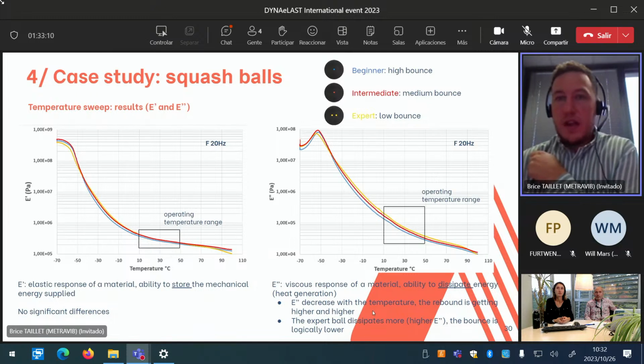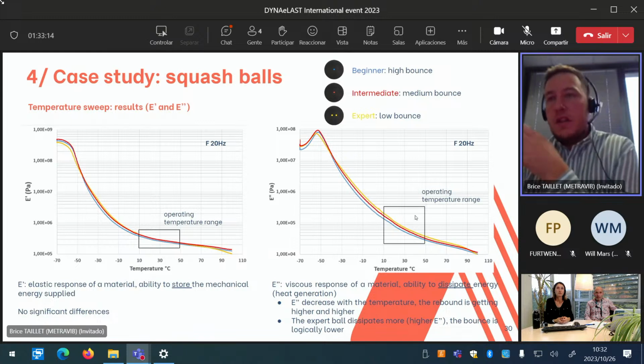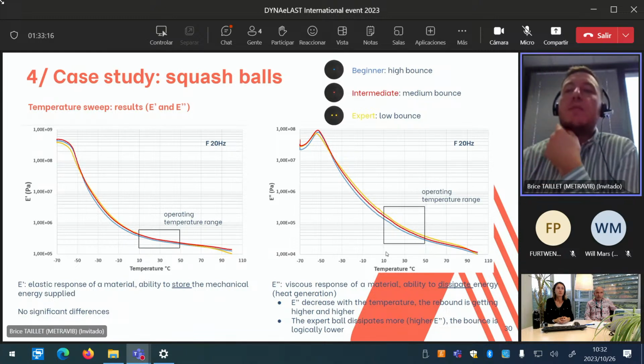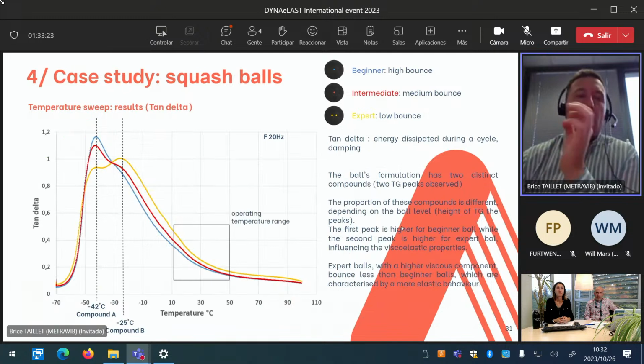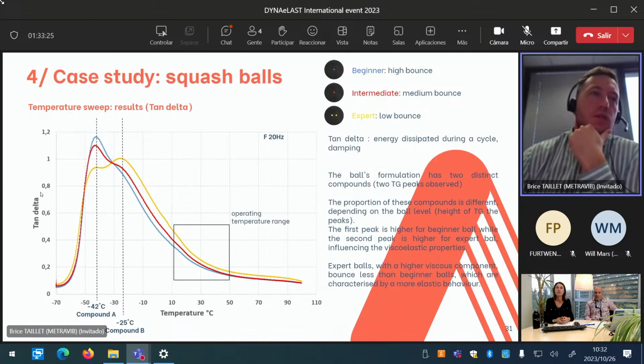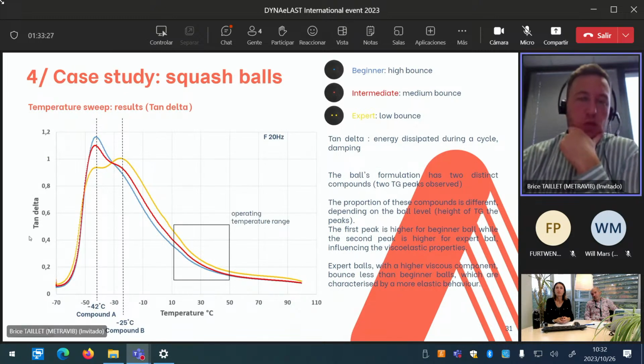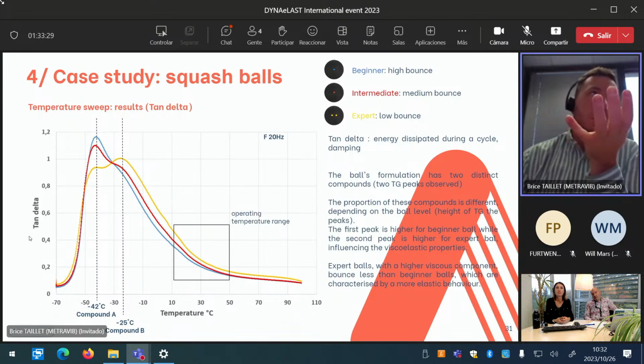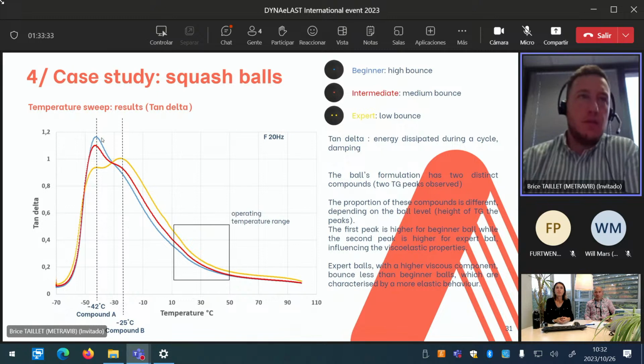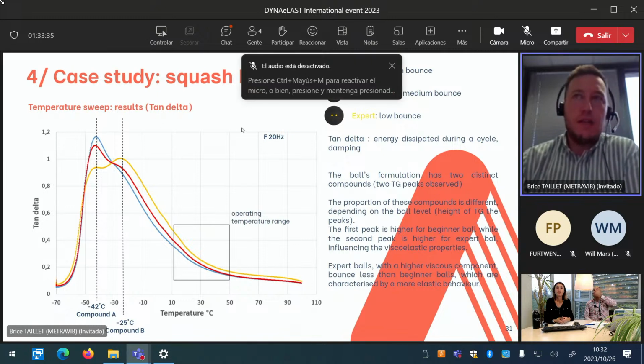Okay, E'' decreases with the temperature. The rebound is getting higher and higher. That's totally normal, and it's not really obvious, but the expert ball dissipates more. The bounce is logically lower, as you can see here. More interesting, if we look at the tangent delta. Tangent delta is a factor corresponding to damping properties. Okay, once again, the blue is the beginner, the red is the intermediate, and the yellow is the expert one.